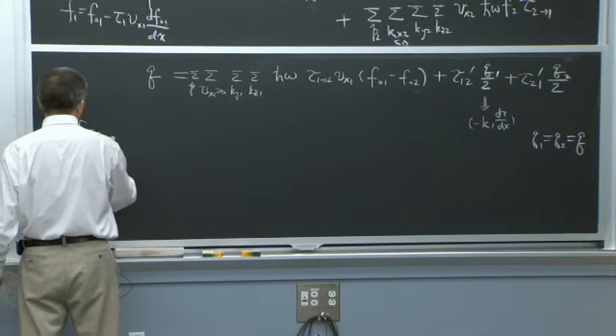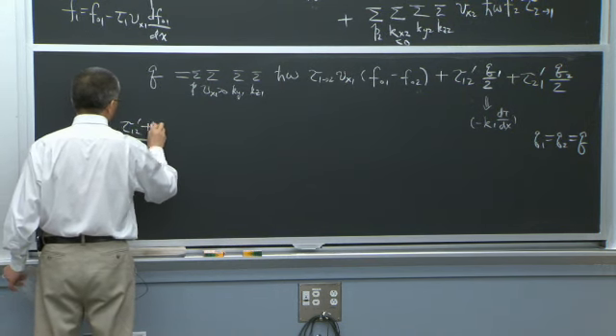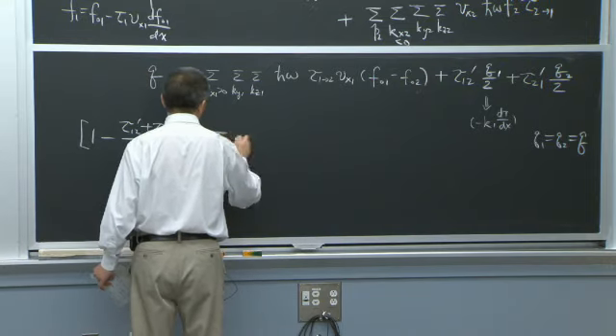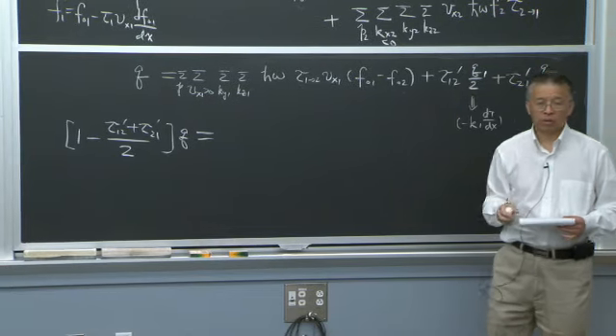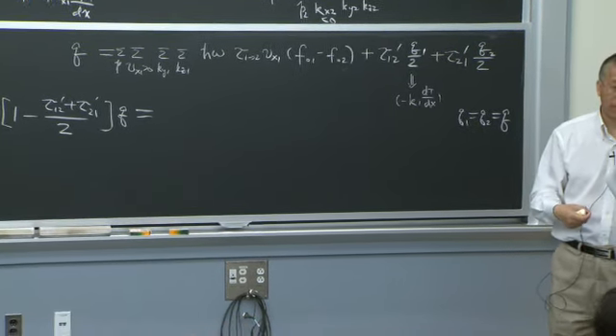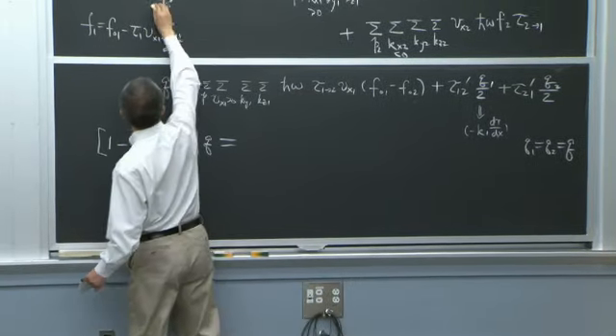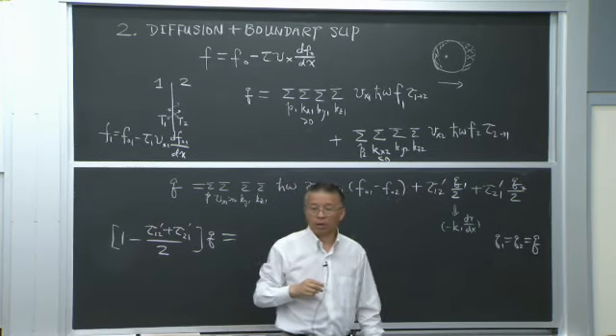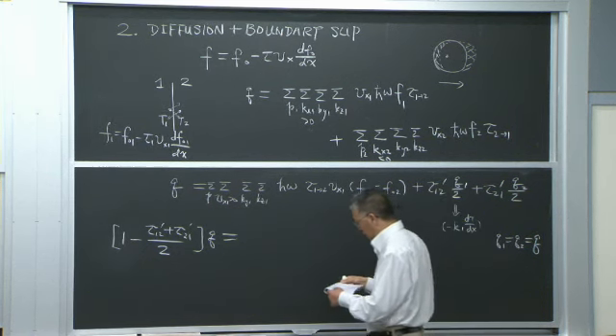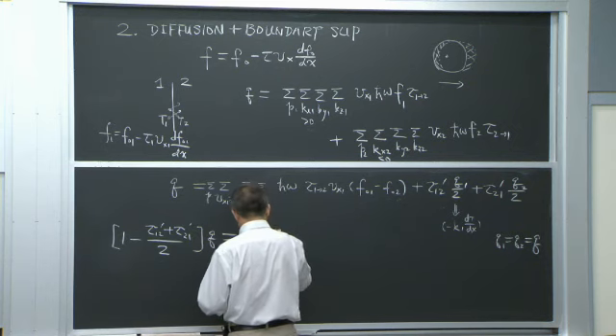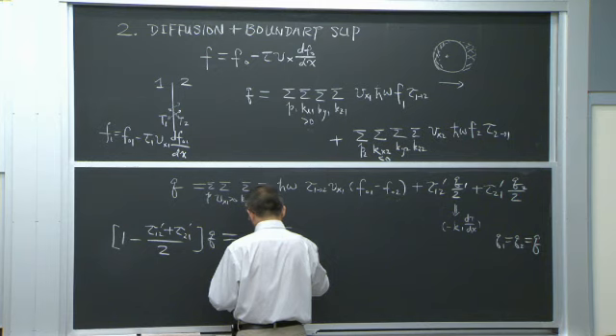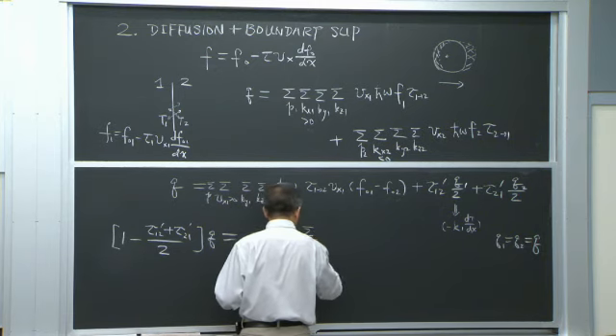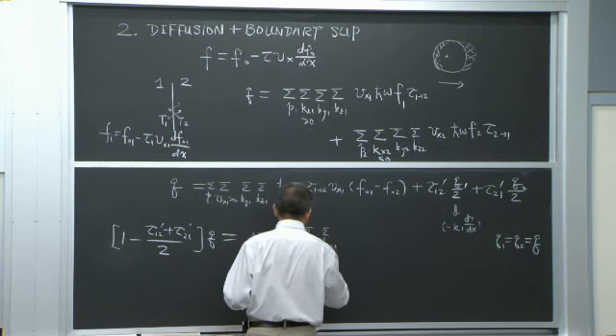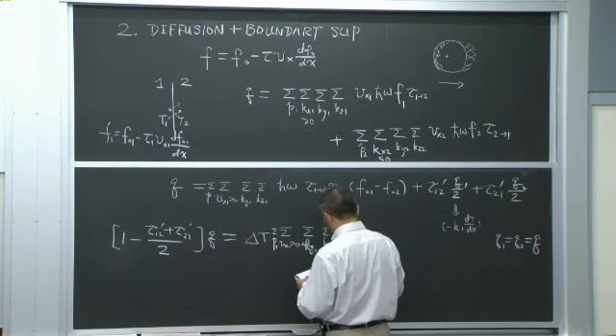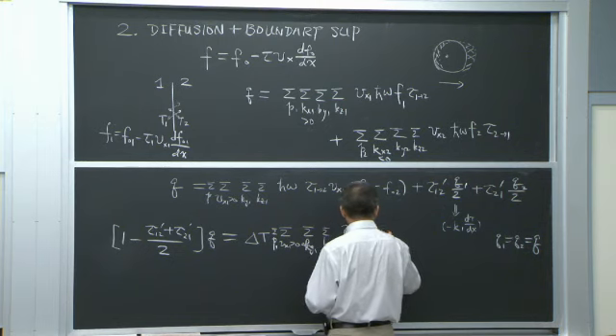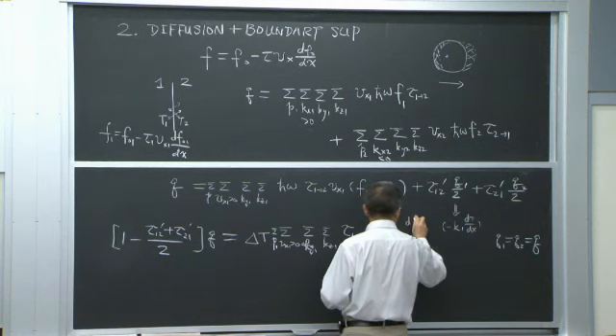So I plug in, I have one half tau 1 to 2 prime plus 2 to 1 prime Q equals. Now F01, F02 is related to the temperature T1 on the first side at the interface, and this is T2, the temperature, right? If the difference is not large, I can write this as delta T, with VX1 larger than zero, and KY1, KZ1, and again you sum up the polarization, tau 1 to 2, VX1, h bar omega, dF01/dT.